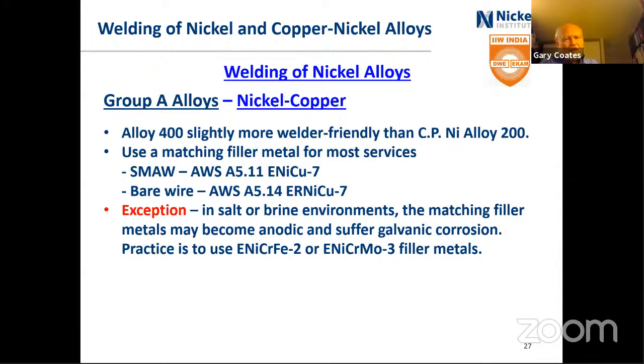and you might think that's the one that is used, but in salt or brine environments, the matching filler metals may be anodic to the base material, and you might suffer galvanic corrosion. And those of you who know a little bit about galvanic corrosion, the worst possible case is to have a small area of material that's anodic, that corrodes preferentially to the larger area of cathodic material, the material that doesn't. And when you have a weld on a piece, that is the small area, so you definitely don't want to do that. Typically, there are 2 filler metals listed there.